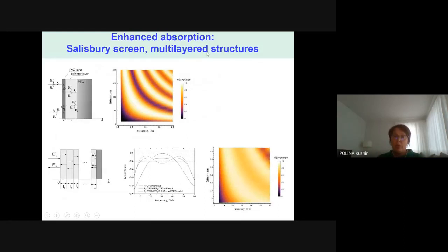If you want to increase it even more, and also reduce the thickness of the dielectric used, to work with just a few tens of microns and not millimeters, if you address the microwave frequency range, you should add a back reflector. Of course not a perfect one, as we know those don't exist, but thick enough to be thicker than the skin depth, in order to provide constructive interference.